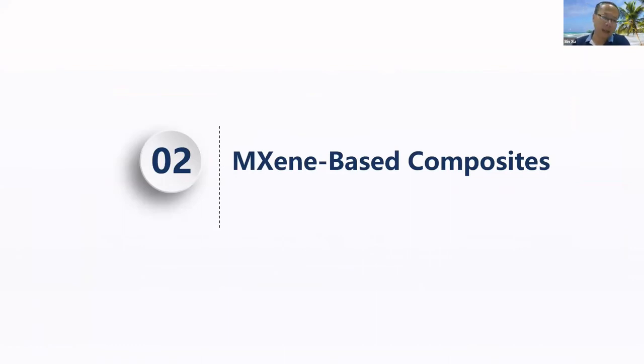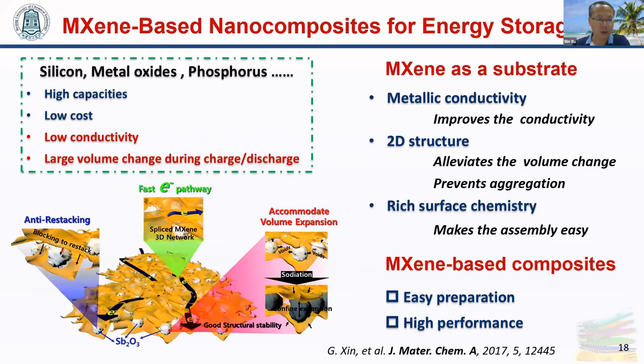The second part is about MXene-based composites. In batteries, some active materials such as silicon, metal oxides, and phosphorus are promising anodes for batteries due to their high capacity and low cost. However, these materials suffer from low conductivity and large volume change during charge discharge.